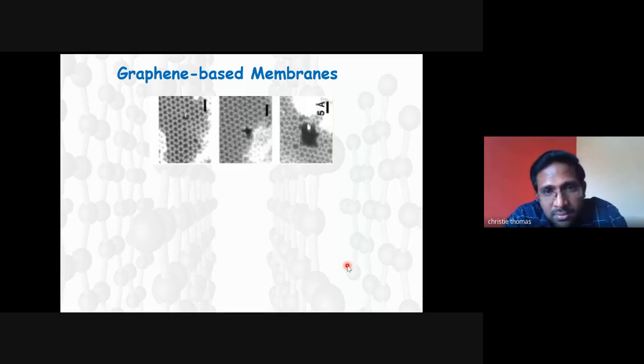But you can put artificial pores on graphene. That's what you see here. Look at the laser pointer. Using high energy radiation, you can put artificial pores on the graphene and make it selectively allow certain molecules to go through. For example, you can control the size of the pores in such a way that it allows just water molecules to pass through and blocks ions. The larger ions will be blocked. Then it can be used as a desalination membrane. It blocks ions and water molecules go through.